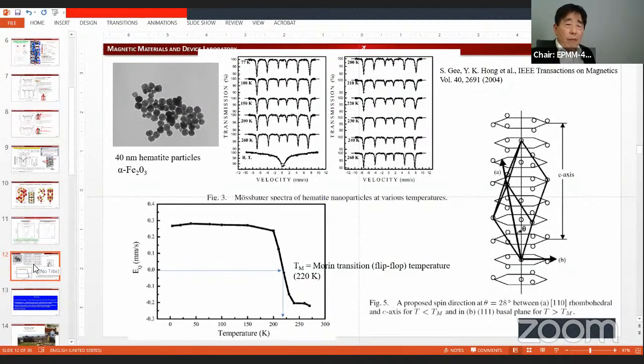Next, a powerful tool of this Mössbauer spectrum is that it can identify the Morin transition temperature. Morin transition temperature means a flip-flop temperature. How can we measure this? This is the quadrupole splitting in terms of temperature. At this zero point, below is negative, above is a positive quadrupole splitting. At 220 Kelvin, that quadrupole splitting changes its sign from positive to negative. That is called the Morin transition temperature.